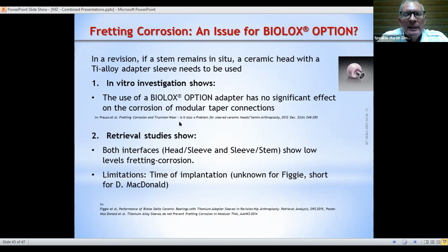Unfortunately, there are not so many explants because there are not so many cases where we use this Biolox option system. There are two main studies, from Figi and McDonald, with limited time of implantation, but both came to the conclusion that at the interface head-sleeve and sleeve-stem, there are low levels of fretting and corrosion. And this is thanks to the fact that CeramTec made the right choice of material. The sleeves are made of the conventional titanium vanadium alloy and not cobalt chrome or beta titanium.